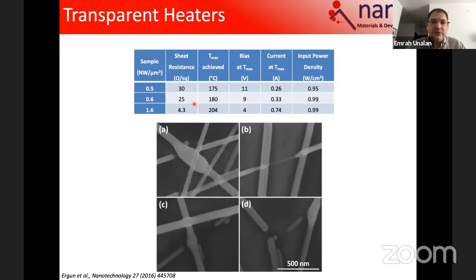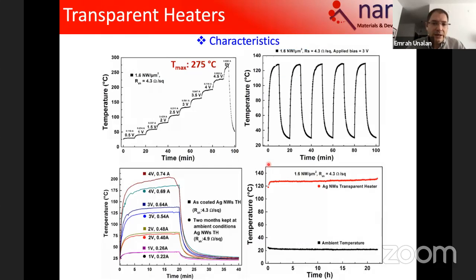And always there is a limit. There's a temperature limit. I cannot go to temperatures of 600, 700, or 1,000 degrees. The reason for that is, as you see, the thinner diameter nanowires get damaged with diffusion, eventually leading to a distortion of the network. But I mean, I can engineer this temperature. So as you see, the previous slide was 200 degrees, but if you do a gradual increase in the potential, the current and the voltage, you can go to temperatures as high as 275 degrees Celsius, which is enough for an iron or some other applications.